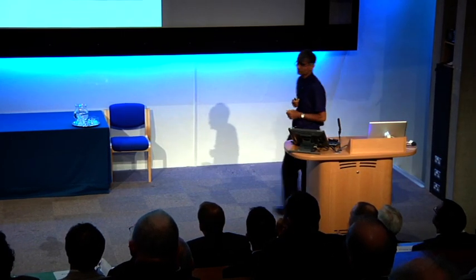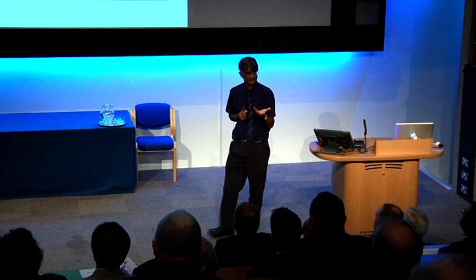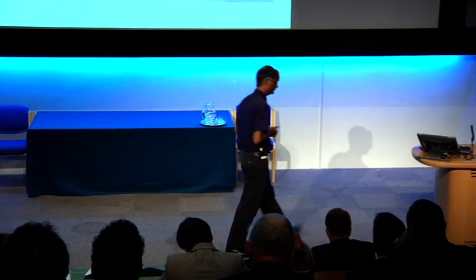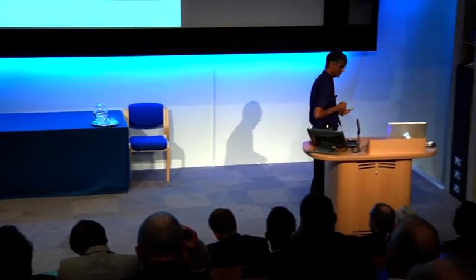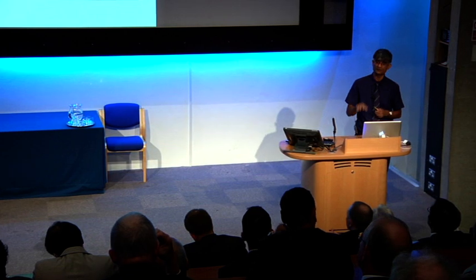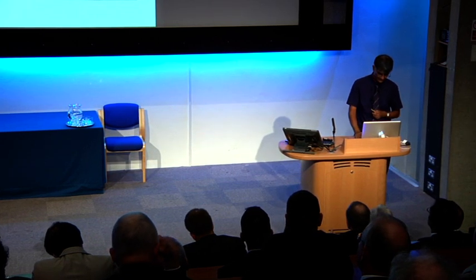Imagine that your cabbage is the cementite. All the leaves are connected in 3 dimensions. You put this cabbage in water, and the water is the ferrite, and the water is connected in 3 dimensions. If you slice it, you see apparently alternating layers of vegetable and water. This is a three-dimensional structure which is very difficult to change by heat treatment, or at least not economical, simply to anneal it until it spheroidises.